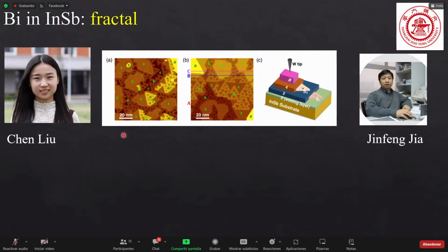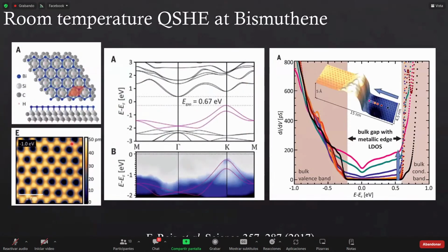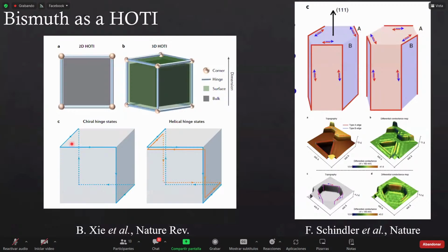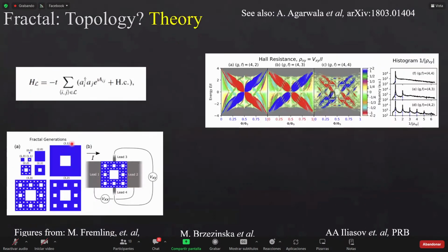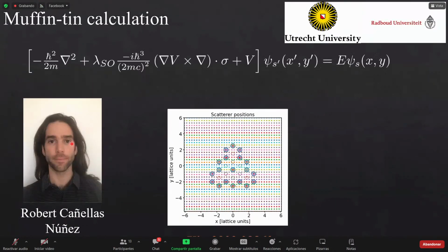spin-orbit coupling. It's the same reason why, when you look at these experiments here, you just need bismuth to see this, because it's a material with very high spin-orbit coupling in a honeycomb lattice. It also forms this honeycomb-like lattice, at least for these substrates. So basically for us, that's the important point. And if you look at the modeling that we did, there's no information on bismuth at all, aside from the fact that it has a very high spin-orbit coupling. So this parameter here will be quite high for bismuth. So if you can have a material that also has high spin-orbit coupling, for us that is the important point. At least theoretically, if you can have a fractal lattice with a material that has high spin-orbit coupling, that is already enough to see the same states.